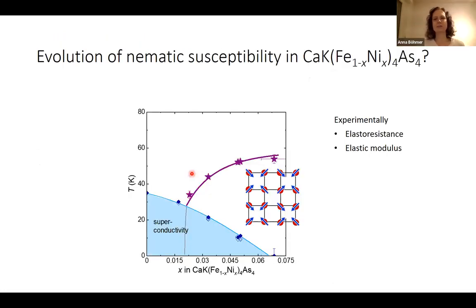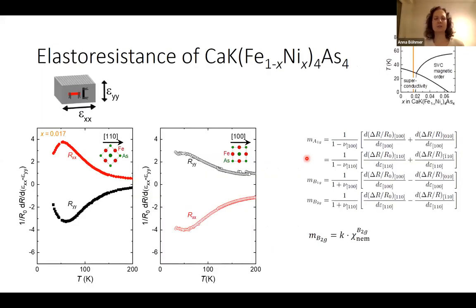But what we were wondering is what will this look like experimentally? So here's our phase diagram again, and I want to emphasize this is a large phase diagram. We go from a TC of 35 to fully suppressed magnetic order. There is no orthorhombicity, there is no nematic order, there is no stripe type magnetic order. So here we are fully tetragonal, and we were still wondering what's the nematic susceptibility in this fully tetragonal phase diagram. And we are looking at elastoresistance and elastic modulus measurements. Elastoresistance I don't need to introduce anymore, thanks to the previous two talks.